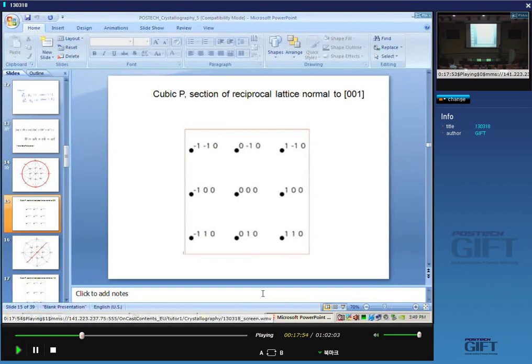So when, for example, you look in your electron diffraction pattern, you're looking at reciprocal lattice vectors, and a spot which is closer to the origin, the transmitted beam, represents planes which have a larger d-spacing. So carbide spots, for example, usually come nearer to the center because carbides have large lattice parameters compared with things like ferrite or austenite. Okay? Of course, this is just primitive cubic, yeah?